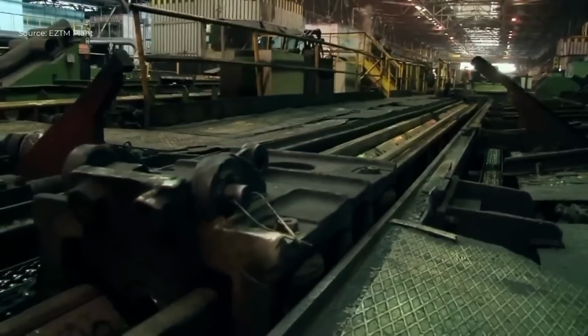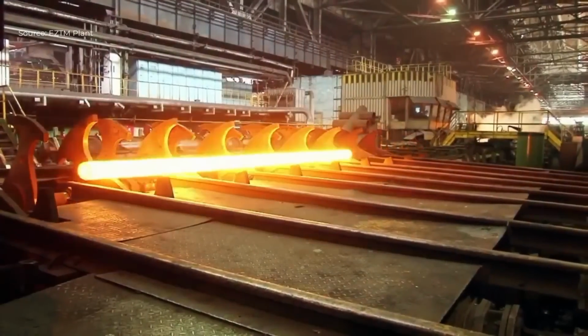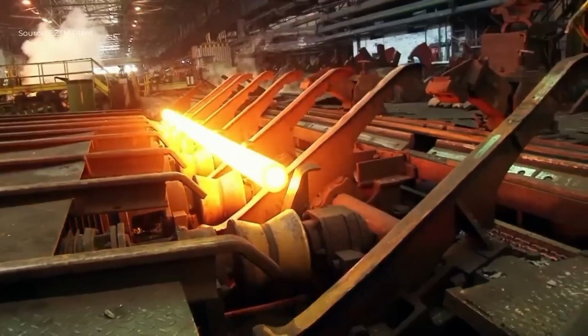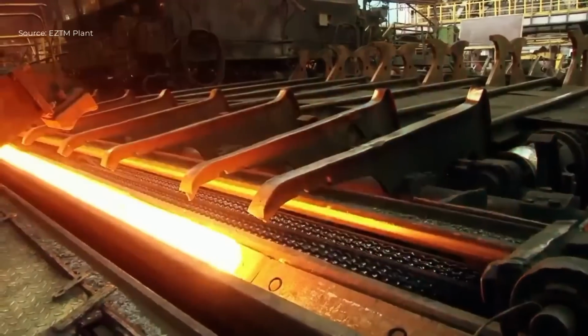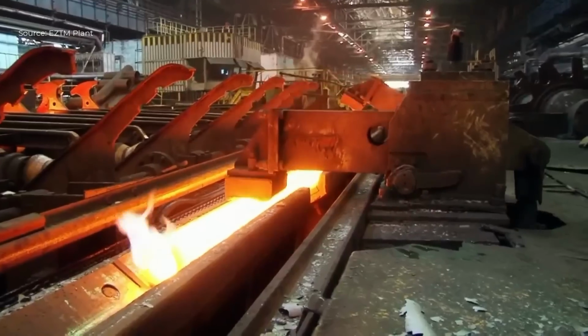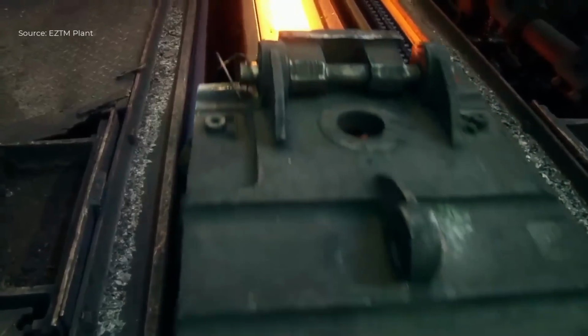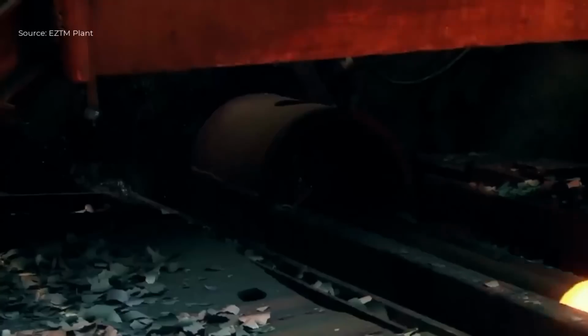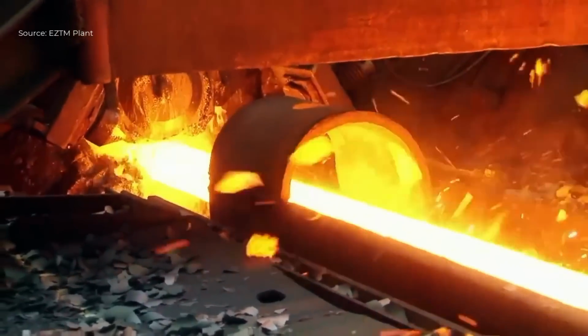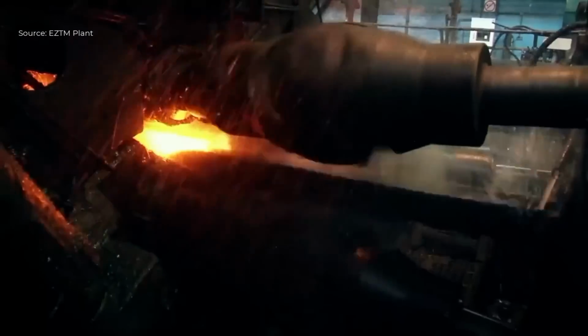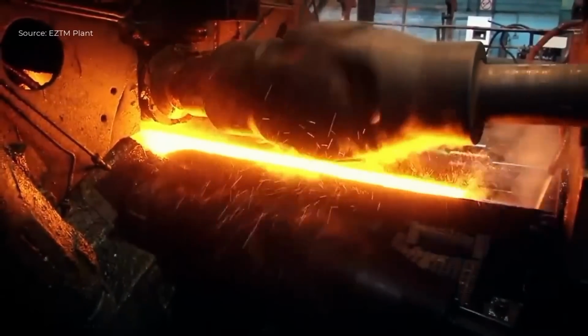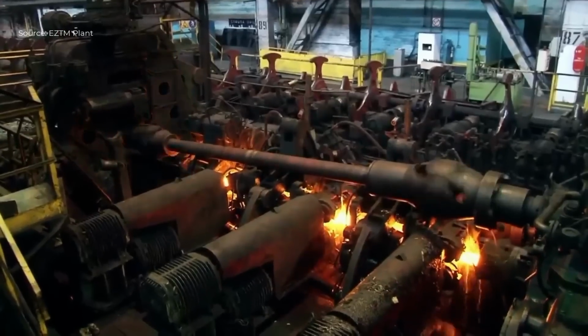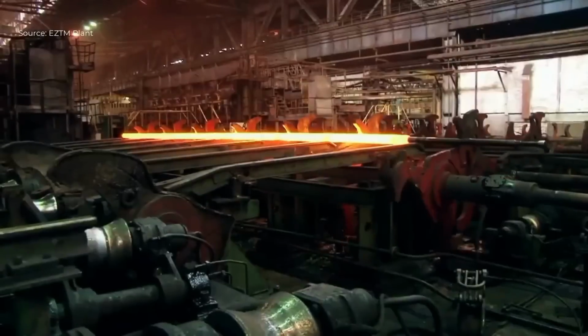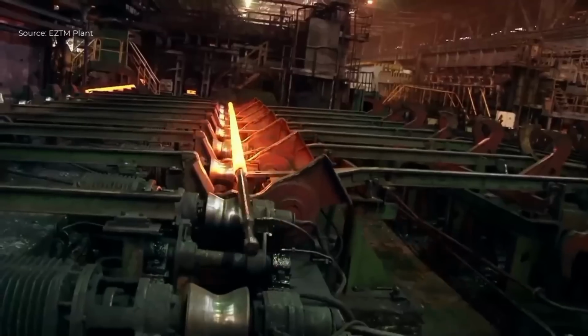These billets are first cleaned and then heated in a furnace to temperatures between 1,100 degrees Celsius and 1,300 degrees Celsius, depending on the steel grade, to reach a plastic state suitable for deformation. After heating, the billet is loaded into the container of the TPA 200 press. A powerful hydraulic ram then pushes the billet through a shaped die.